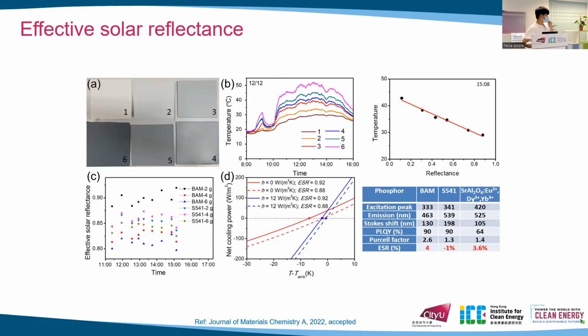Commonly we measure the solar reflectance directly using a UV-visible-infrared spectrometer, but this machine cannot recognize the fluorescence contribution. So we made 6 reference samples with different solar reflectance and without using phosphor. By measuring their temperature, we can fit a relationship between the temperature and the solar reflectance, and then we can obtain the effective solar reflectance of the fluorescent coating by measuring its temperature.